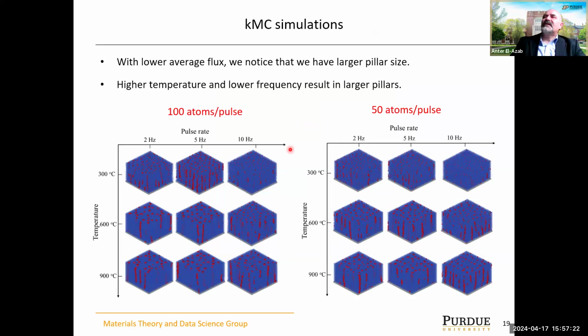The next thing is to look at the deposition parameter effects on how these pillars self-organize. The self-organization here means the density of the pillars, the size of these pillars, and whether there is a particular order on the surface, like a pattern, like a square pattern or a hexagonal pattern, a random pattern or a quasi-random pattern on the surface. That is sensitive to the amount of mass you deposit per pulse, the pulse rate, the substrate temperature, and so on. So this is like a catalog of the morphology dependence on the amount of atoms per pulse versus temperature, from high to low number of atoms per pulse, in the temperature and frequency space of the laser pulsing, basically.